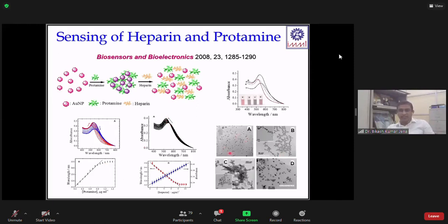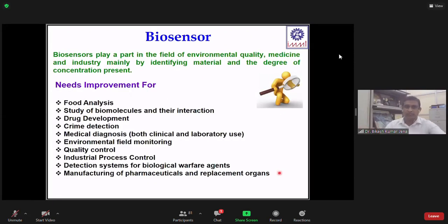So you can see here the nanoparticle is initially like this. They are somehow at different distances. But when you add some protamine, you can see some aggregation takes place. The color looks like this. When you add high concentration, strong aggregation takes place. But when you add heparin, you can see de-aggregation takes place. By this aggregation-de-aggregation method, we are able to use this nanoparticle for optical sensing of polyionic drugs.